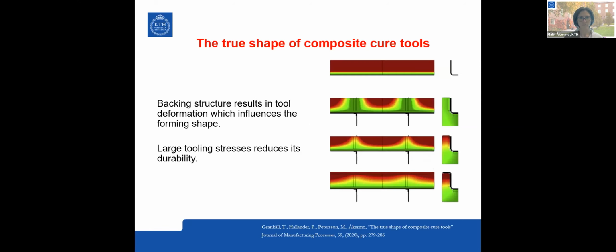And we can find that compared to a simple L, which looks like that, depending on how hard you fit your backing structure with your curing structure, you will have quite high stresses in your material. And today, composite tooling is considered very good, but maybe not as durable as you would expect. And we can actually see one of the reasons in this study.